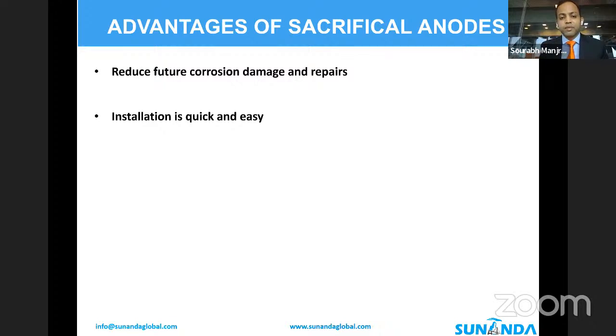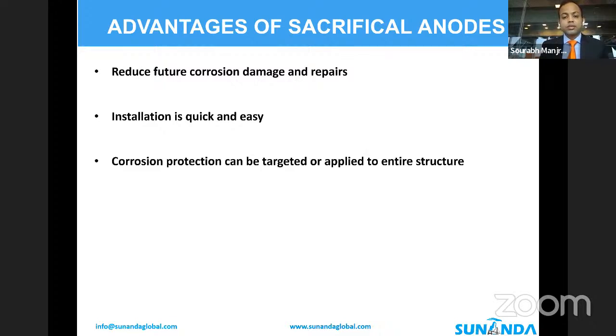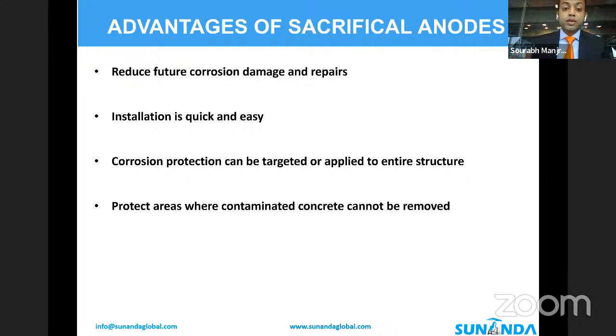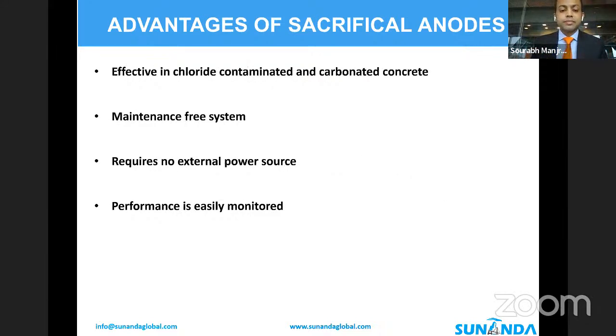Their installation was very quick and easy. Corrosion protection could be given to targeted areas as well as the entire structure, depending on what the requirement was of that particular structure. It could protect areas that were contaminated as well. There was no need to remove the contaminated concrete, or sometimes it wasn't possible to remove the contaminated concrete. Effective in chloride contaminated and carbonated concrete, maintenance free system, requires no external power source, and the performance can be monitored as well.